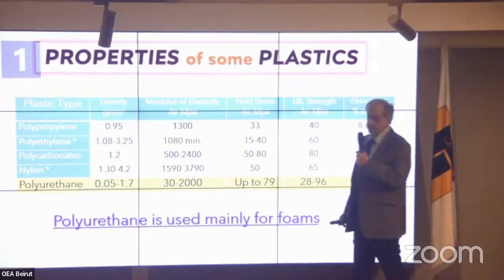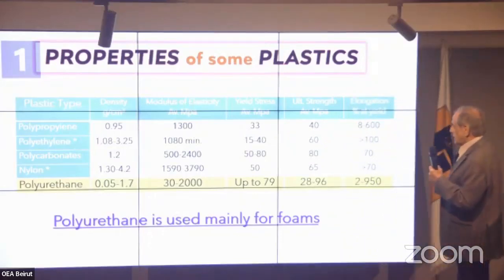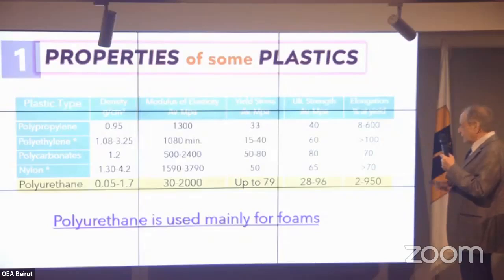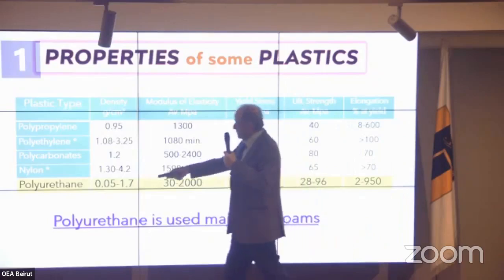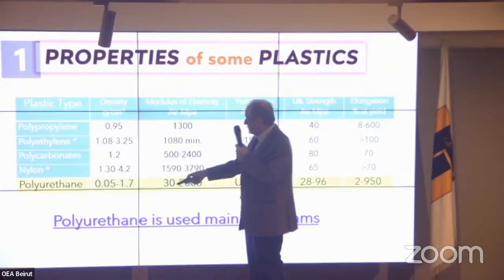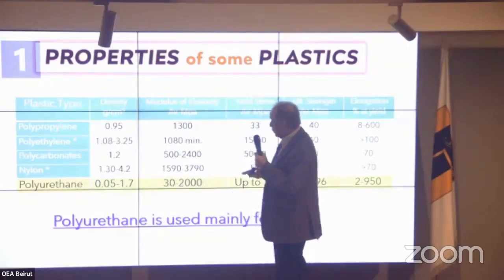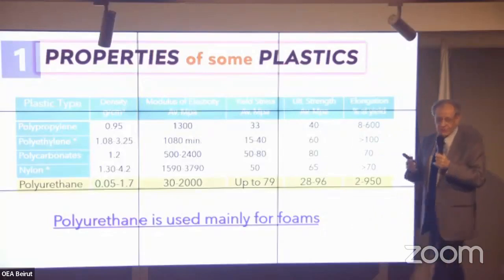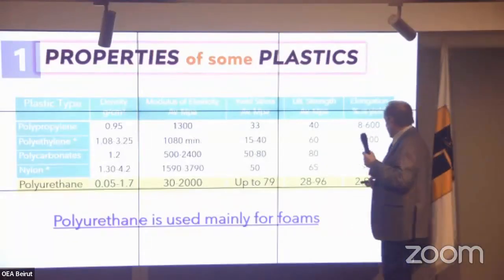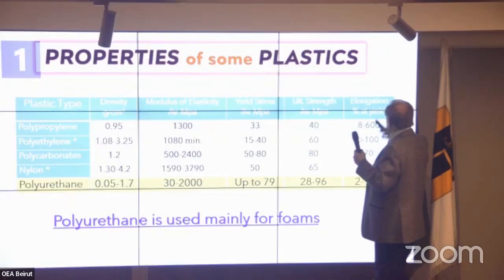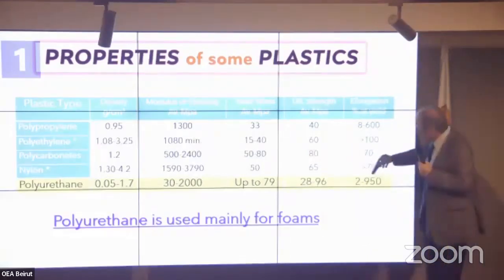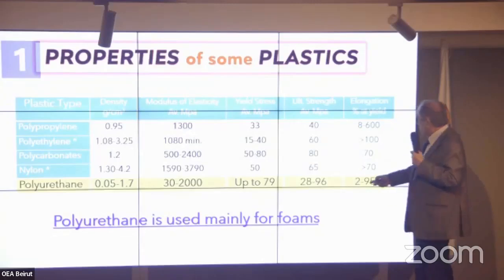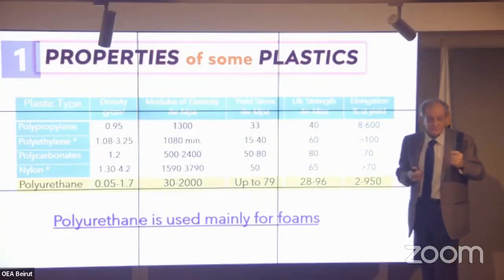Now, the polyurethane is a material that varies too much, really varies too much. It can be of very low density to very high, and it can have a modulus of elasticity between 30 and 2000, which is too much in range. And the elongation can go down to 2%, which is very low, to 950%, which is extremely high.